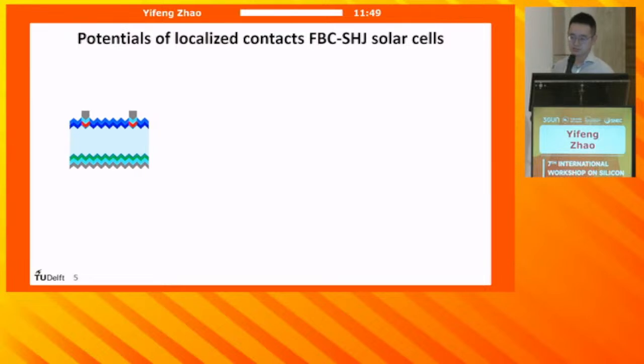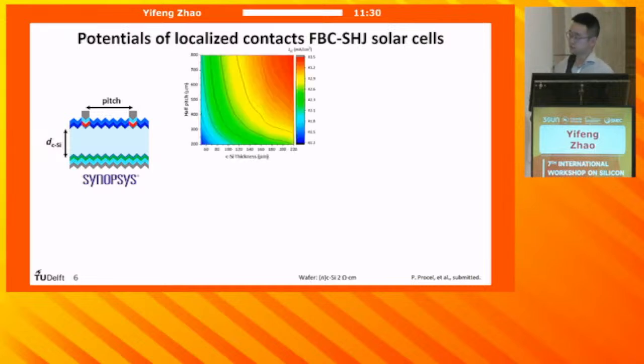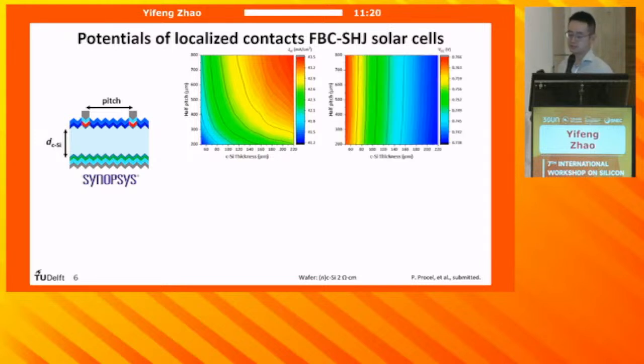To understand the potential of localized contact heterojunction solar cells, we performed TCAD Sentaurus simulations. Here we varied the pitch of the design and also the thickness of the wafer. Here I will present the simulation results of the solar cell performance. First, the JSC gets higher when you use a thicker wafer and a larger pitch, which is expected. And the VOC gets higher when you use thinner wafers, while not being very sensitive to the pitch size variations.